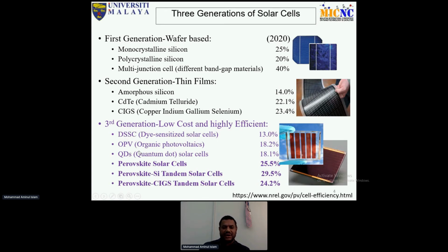But later on, when organic photovoltaic and quantum dot cells come, their efficiency is around 18%. The latest technology is the perovskite type solar cell, and you can see very quickly the efficiency reaches 25.5%. That's only the perovskite solar cell, which is higher than any of them. When you make it tandem, like a multi-junction with silicon, it comes to 29.5%, and when we see CIGS, it's 24.2%.